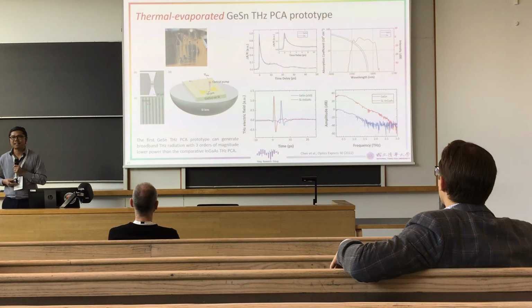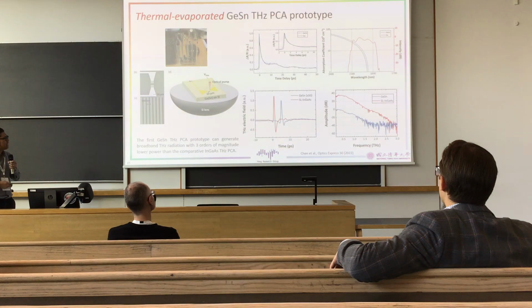To have the proof of concept, what we are doing is we mix germanium and tin and we cook it. We are using a thermal evaporator to evaporate it. And this is not crystalline, I mean, this is amorphous germanium. But we still can get the ultrafast response, and you can see the terahertz pulse. It gets some radiation, with 3 orders of magnitude lower power than the indium gallium arsenide ones. But this is the first in the world, and you get what you get. And we know how to improve it.